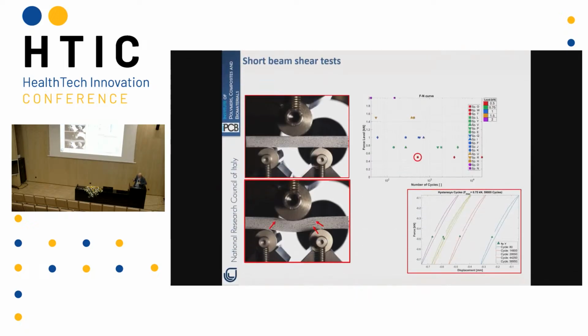In fact, when you try to make a fatigue test, which are the tests that can give you information about the durability of your material in a real situation, you observe that your samples collapse. There is no collapse of the carbon fiber, but of the shear, between the different layers of material. So this has a strong effect on the durability of your samples.